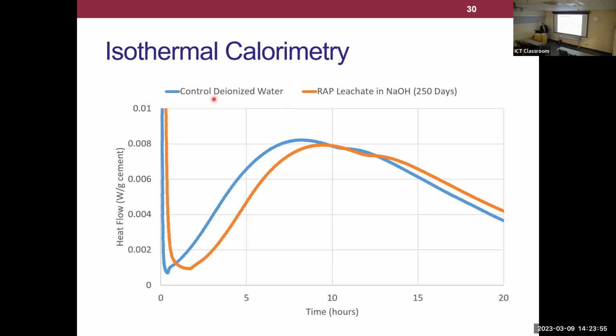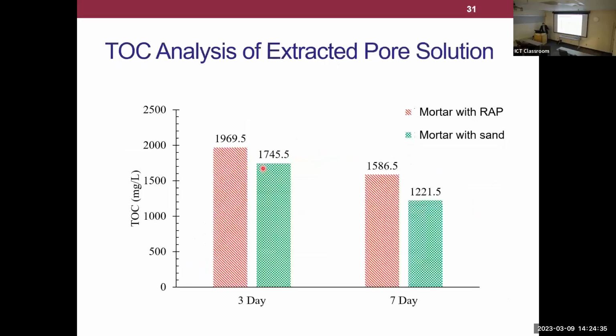What we're seeing here is a control sample where we just mixed cement powder with water, and then the orange line is where we mixed cement powder with that NaOH solution that had the organic leachate. And what we're seeing is a shift. This main peak is our main hydration peak of cement. We're seeing this peak shift to the right, which basically means that we did delay the rate at which cement hydrated. So there was some retardation, some change to how the cement was hydrated. We did delay it slightly. So now we have an idea that maybe this hypothesis does make sense.